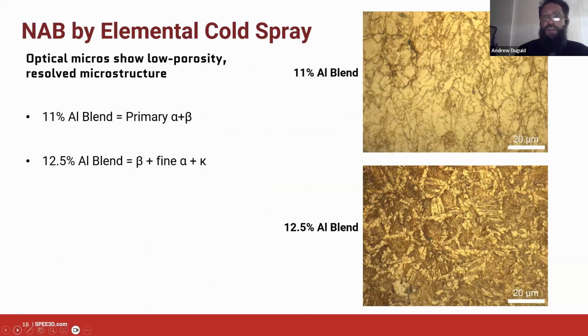Okay, so here is where we started to really dig into developing the alloy and starting to tune the alloy constituents. And again, this is why we start to look at what are we getting and what do we need to adjust. So, 11% aluminium blend: we've got a fairly homogeneous microstructure that's all primary alpha with a little bit of decomposed beta phase in it, where you can see the scrubby bits that'll be decomposed beta. So it's a little bit higher and precipitates.